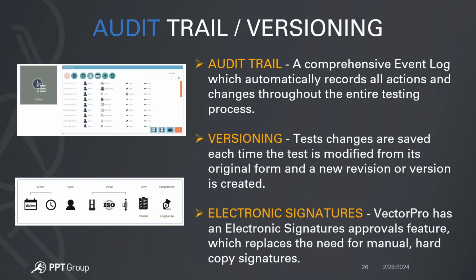The second part is also the versioning feature, which means essentially the test changes are saved with notes each time a test is modified from its original form and a new revision or version is created. For instance, if you ran a test, typical, let's say a CRC test, and you ran it initially at 10 revolutions per minute, but then you realize that running it at, say, 5 revolutions per minute of rotational speed gave you more consistent results, and that was a little bit more similar to what would happen in real life by humans, then that original test modification from that initial speed of 10 revolutions per minute to 5 revolutions per minute would create a different version 2 of the test procedure.